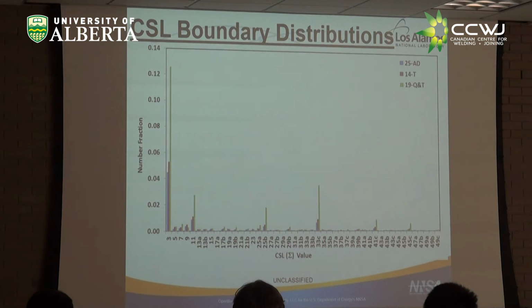CSL boundaries, again, are coincident site lattice boundaries. And the point to notice here is that in the quenched and tempered, which will be in the green over here, there are sigma 3 boundaries, and I think a sigma 9 or a 10. Those are all characteristic of martensite. So there's tons of martensite in the quenched and tempered, as there should be, and not in the as deposited.